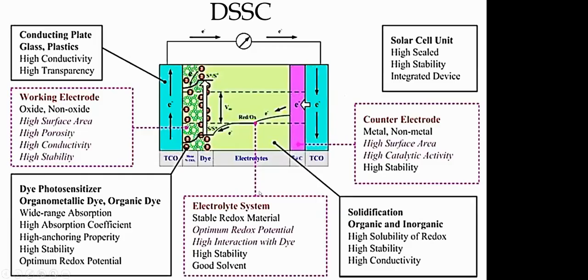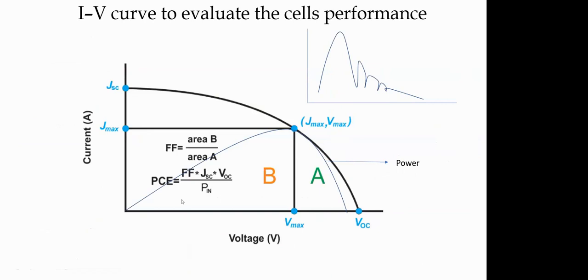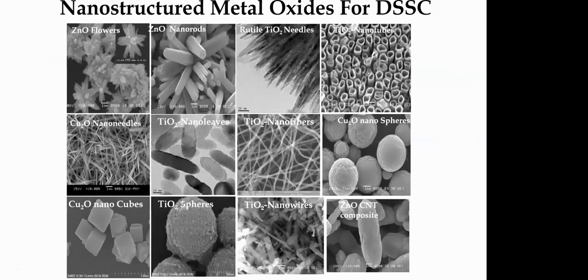So these are some examples of metal oxide nanoparticles which are used as an electron transport material. They include anything with a wide band gap, where the band gap is close to 2 electron volt, 3 electron volt. You can think of a new metal oxide or other semiconducting material in nanostructure form as a new electrode material for electron transport in dye-sensitized solar cells.